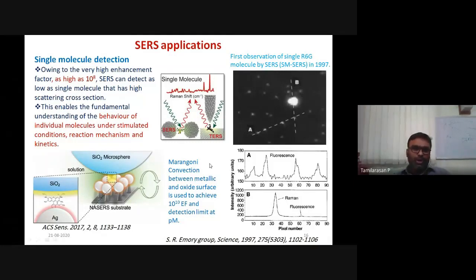And there is also another way to push the single molecule towards the SERS substrate, because for single molecule analysis, they always use picomolar or femtomolar solutions of any Raman probe molecule like Rhodamine 6G. But pushing the molecule into the hotspot is very difficult. So for that, they have used Marangoni convection, where the surface tension of two different structures will play a role. So what they have done is they took a metallic nanoparticle substrate, and then they put a SiO2 microsphere on that. Because of the surface tension gradients, the molecules were pushed into the hotspot. And in this method, they got an enhancement factor up to 10^10 times.